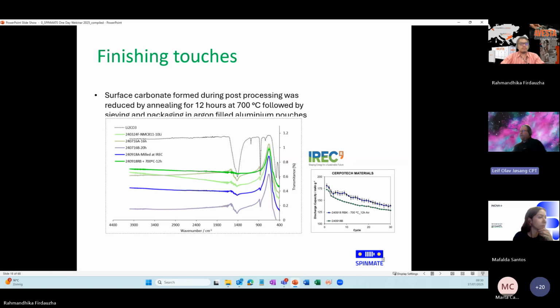So we tested annealing the powder for 12 hours at 700 degrees following the sieving, and you can see the top green line here. The CO2 peaks are at 1400 and 900, I believe. In the top green line, you can see that it has been more or less completely removed, and this also gave better electrochemical performance for the powder. So we introduced that as our second to final step.